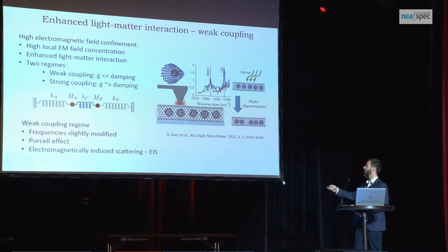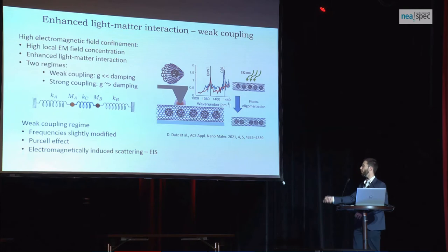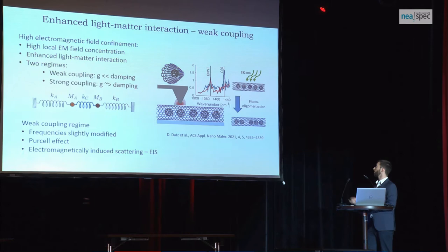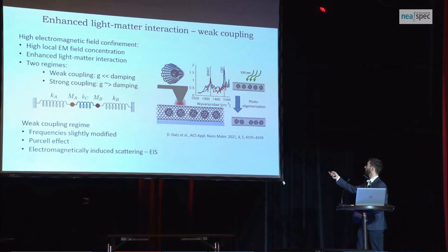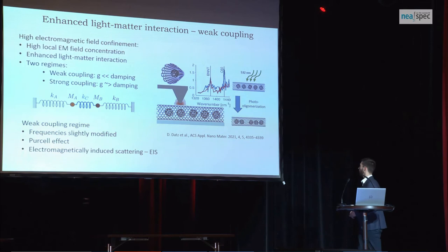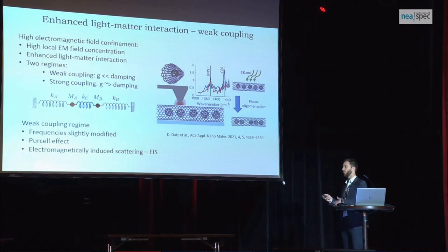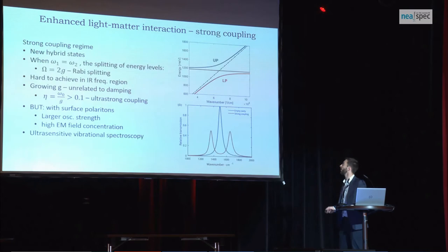In the weak coupling regime, the eigenfrequencies of the two independent oscillators are only slightly modified, but we can still see some very interesting effects like the Purcell effect and electromagnetically induced scattering. We already showed that using boron nitride nanotubes with fullerene molecules, we could see an enhanced signature of the buckyball vibrational signature, and we were able to detect a few hundreds of these molecules.